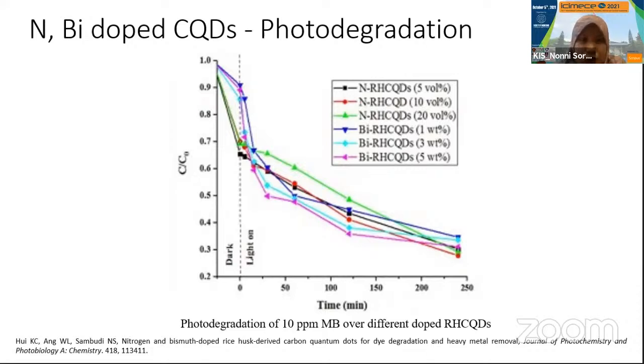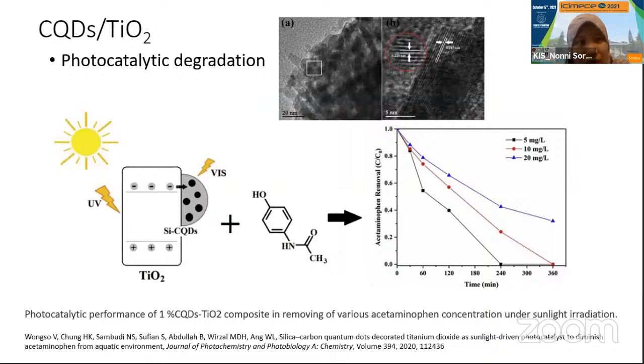Okay, so we agree with the strategy that is done by the other scientists. It is better for us to use the carbon quantum dots in combination with other photocatalysts, so the CQD can do its job as sensitizer. Okay, so what we do next, we combine these carbon quantum dots with titania. So we hope that the titania that has been decorated on its surface with the carbon quantum dots, the carbon quantum dots can act as a bed for the electron that's already excited to reside in the carbon quantum dot, and then later produce the radicals through the reduction process.